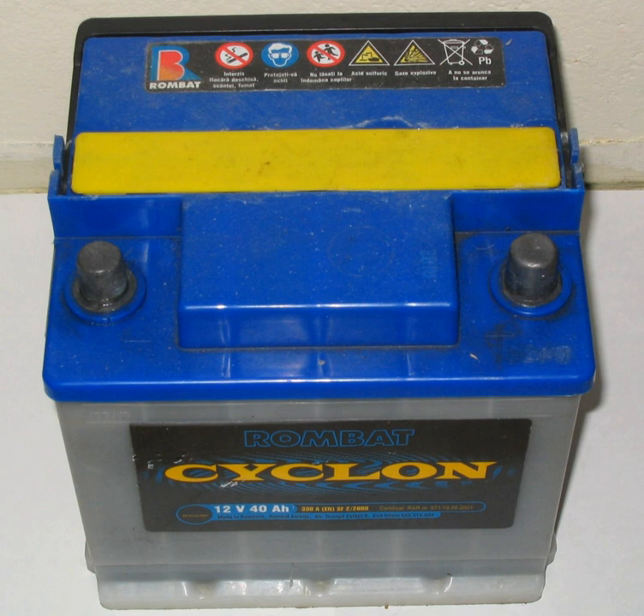These issues were identified by U.B. Thomas and W.E. Haring at Bell Labs in the 1930s and eventually led to the development of lead-calcium grid alloys in 1935 for standby power batteries on the U.S. telephone network. Related research led to the development of lead-selenium grid alloys in Europe a few years later. Both lead-calcium and lead-selenium grid alloys still add antimony, albeit in much smaller quantities than the older high-antimony grids.